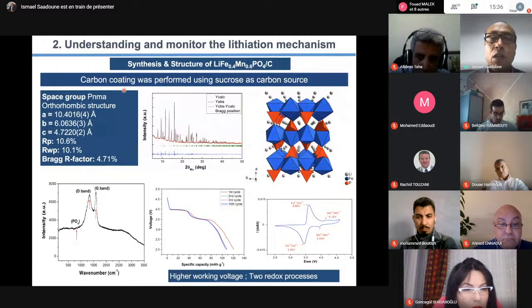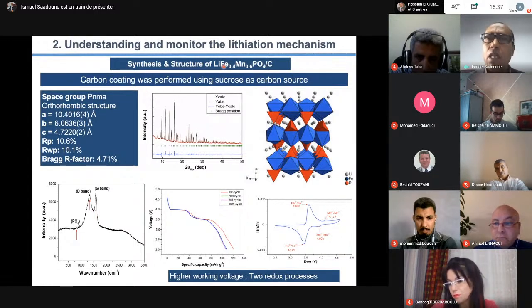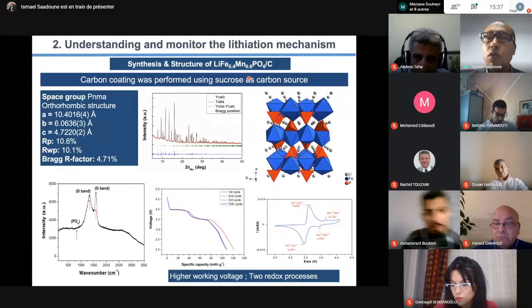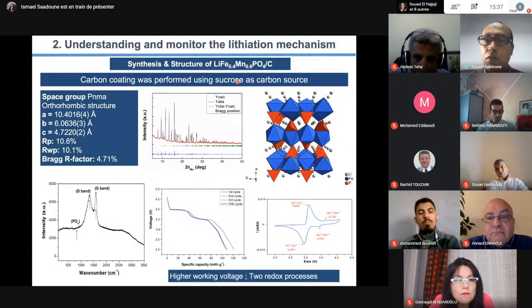So this material was prepared in the lab under some special conditions, and then as phosphate has low electronic conductivity, we use sucrose from the table, as a carbon source to put carbon and to make pyrolysis around the particles.